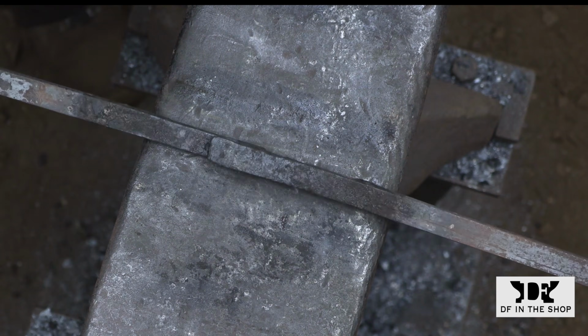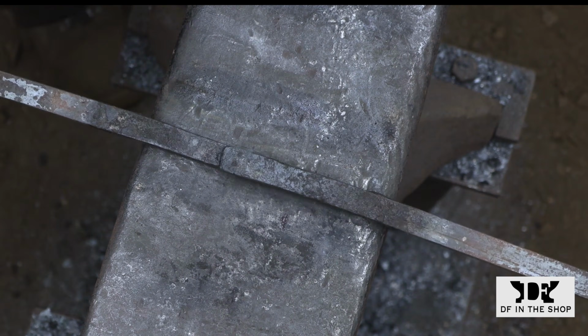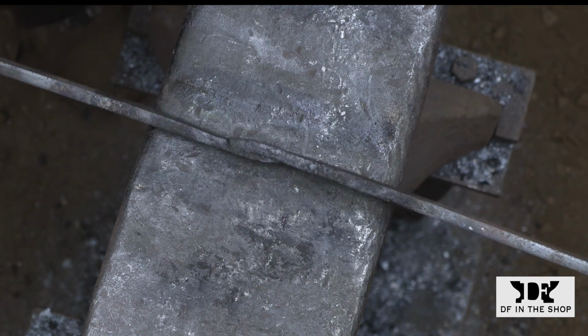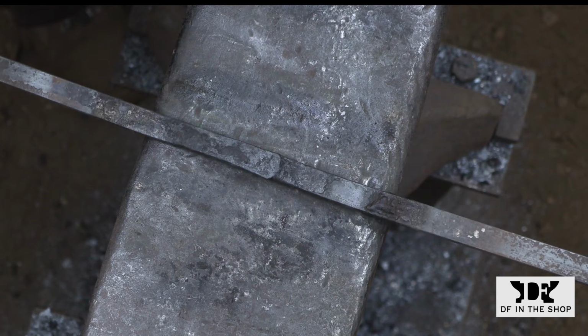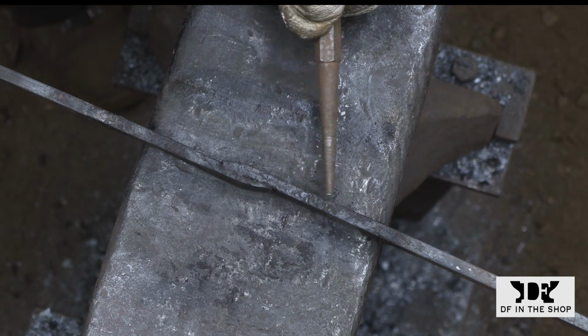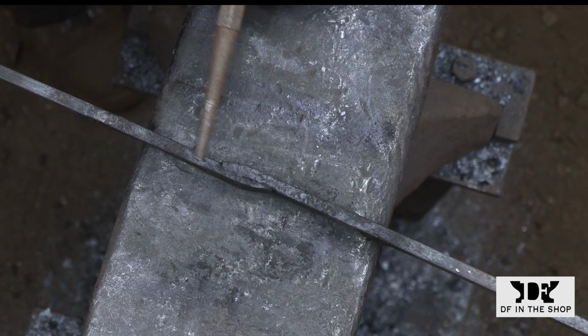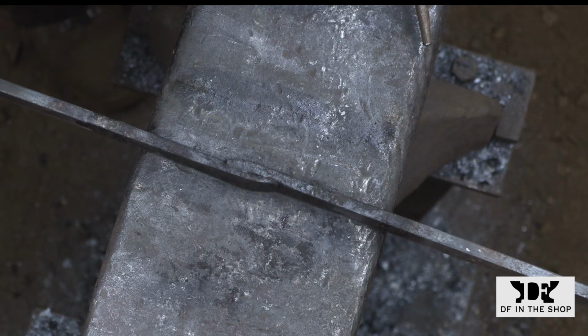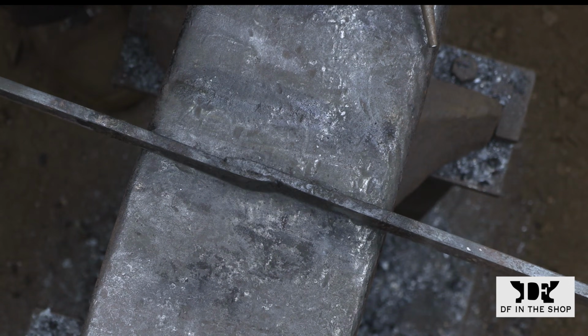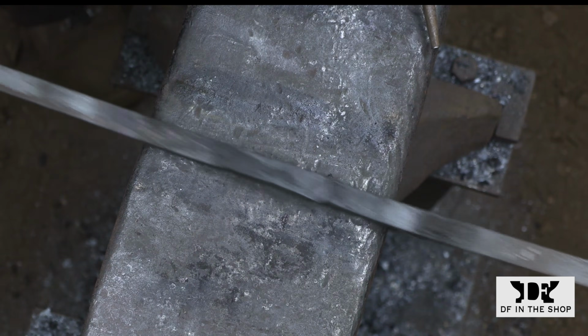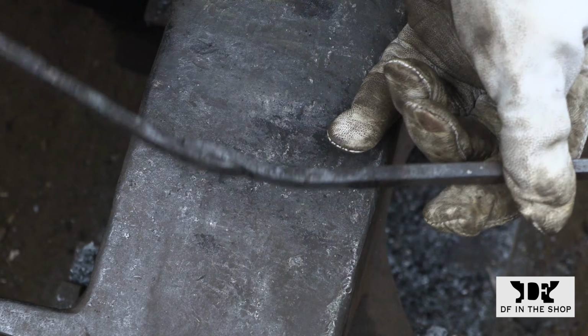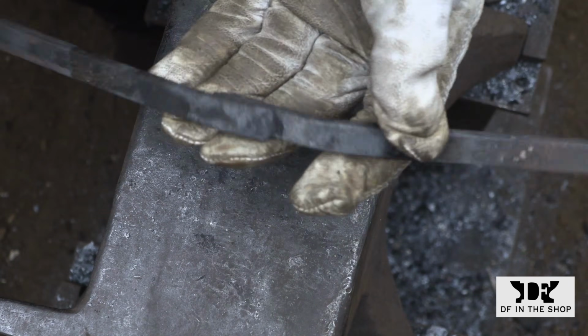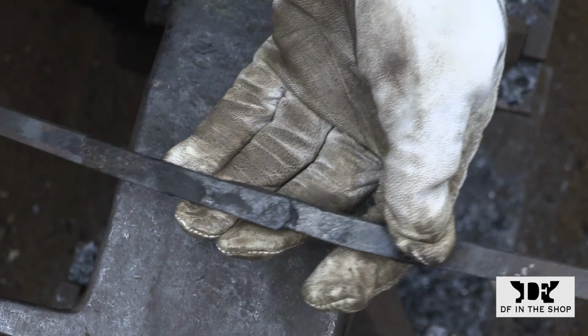So this is the finished weld. It's not as clean as the first weld that I did with new material. There's obviously a bit of evidence of pitting and a little bit of damage done from the first two failed attempts at sticking this weld. But there are edges that are starting to blur, and the bend test does show that I did get good surface contact and there is the potential to have a good weld here.